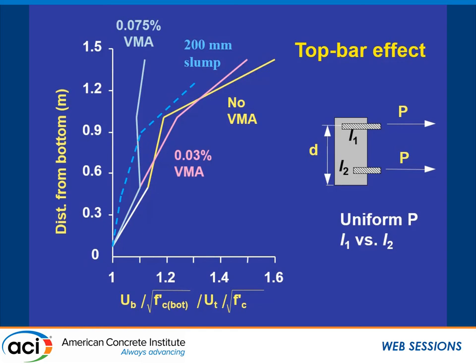And that is the pull-out. This is the top bar effect. So most of the codes say if you have a member where you have more than 12 inches of concrete underneath it, you have to embed your rebars about 1.3 or 1.4, depending on the code. So here we see that the concrete with very low surface settlement has top bar effect less than 1.1. It's completely uniform. The concrete that shows more surface settlement, the top bar effect is going to be affected.